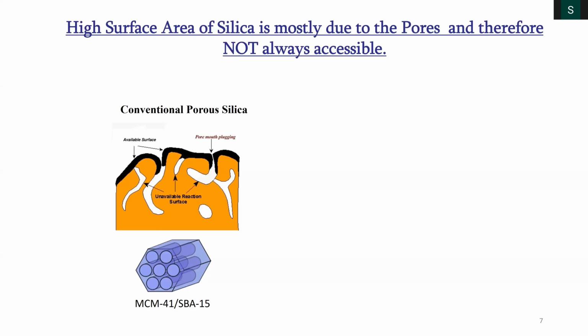However, if you look at the literature, there are lots of high surface area materials. Most of them are because of the porosity, right? If you look at a metal organic framework, they have a huge surface area, but most of them are microporous materials, with pores of less than 2 nanometer size. So the accessibility of that surface area is difficult, right? There is a diffusion issue.